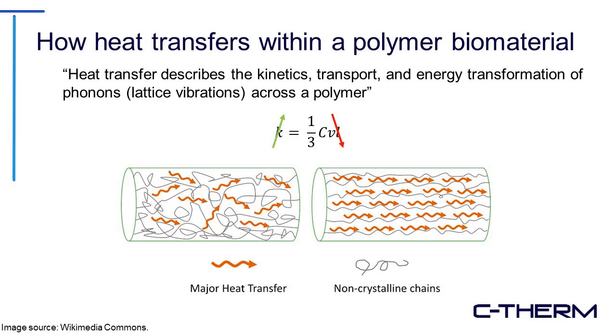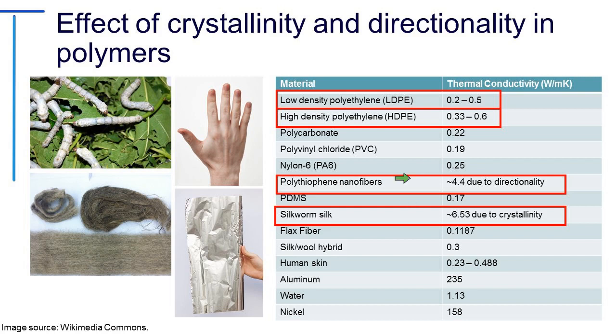Additionally, we can look at the orientation of the chains and amorphous domains of polymers themselves. When you have a random assortment versus a more aligned polymer system, the thermal conductivity can drastically change. We have a lower thermal conductivity in a random chain orientation versus when we're more aligned in one direction for thermal conductivity.